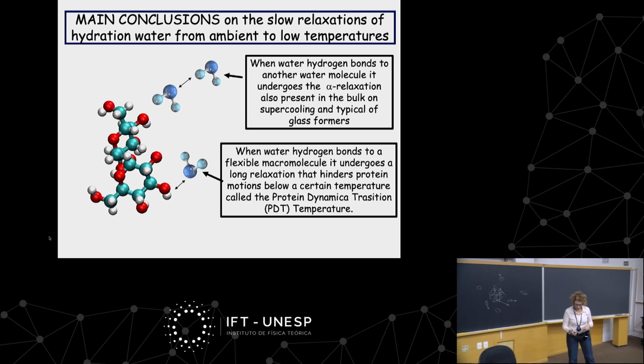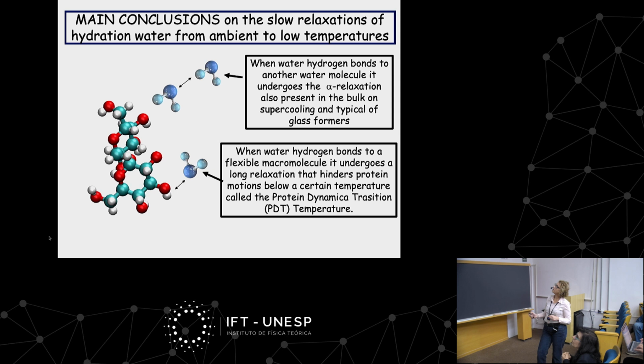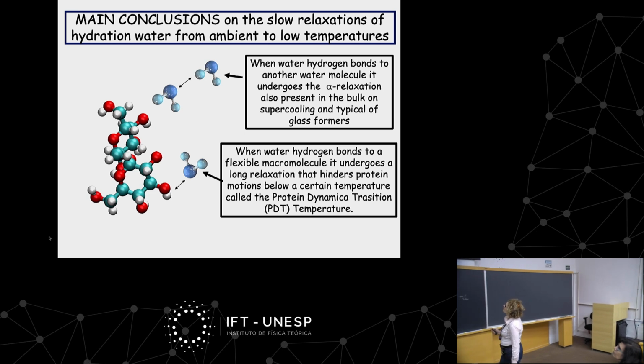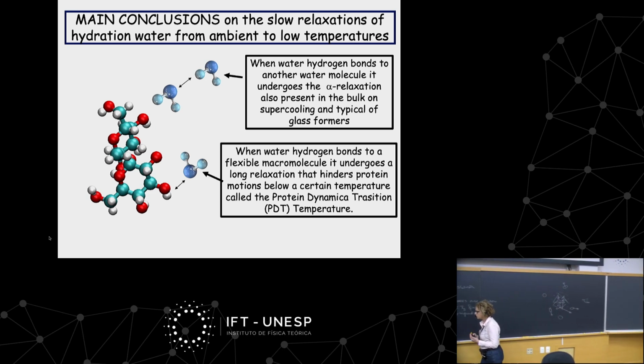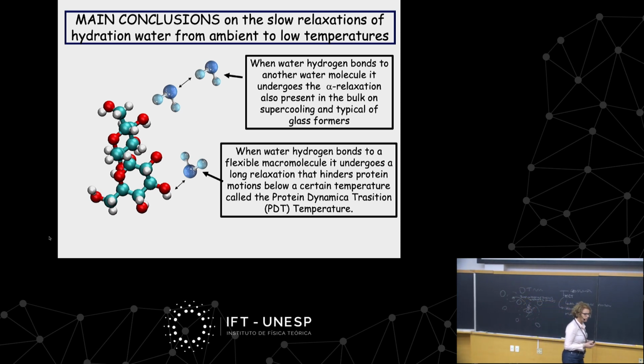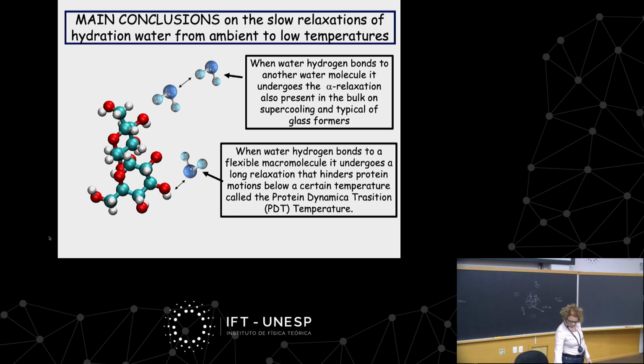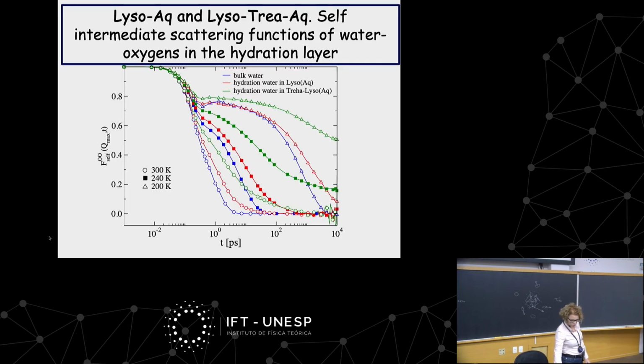Okay, so this is the take-home message, and with this I finish, of the results that we found. We saw that when water hydrogen bonds to another water molecule, it undergoes the alpha relaxation, which is this relaxation of glassy dynamics, but when it hydrogen bonds to a flexible macromolecule, it has another relaxation, which is not the cage relaxation, that hinders the protein motion. And this happens below a certain temperature, which is called the protein dynamical transition. So we think that this particular temperature that was discovered for proteins has very much to do with the properties of water. These are the correlators I told you about with bulk, hydration water, and lysozyme water. And we fitted that to stretched exponentials and two different relaxations, because we have an extra relaxation here.